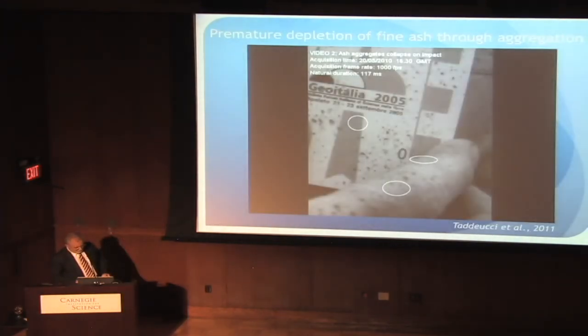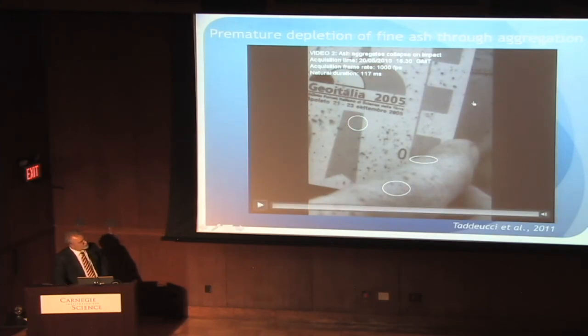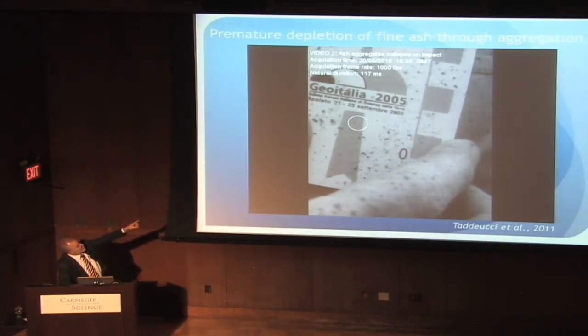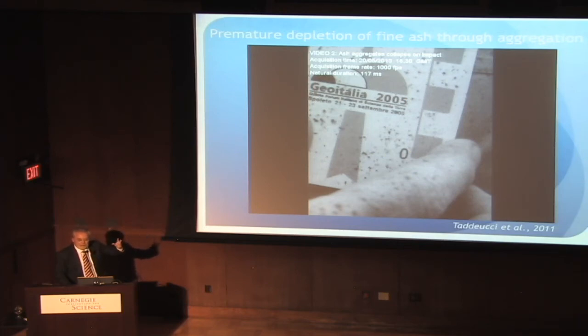And one effect that I want to show you is in this video. If you look carefully, there are 3 circles. Each one of them will show you something happening just near Eyjafjallajökull as it was erupting, and you get the picture right away. The first one, see it? The second one, you see it? Third one, boom. These are falling out of the sky right next to Eyjafjallajökull. By the time the third one fell, you probably saw it was a large clump of stuff that fell, and when it hit, out of its own weight, the impact blew it into 100 or 200 particles. These ash particles are aggregated to 100 or 1,000 times their original size. It means their fall velocities and everything are completely unaccounted for in a sensible way in the modeling of volcanic ash cloud distribution. So there's a lot of work to do on how ash aggregates as well.